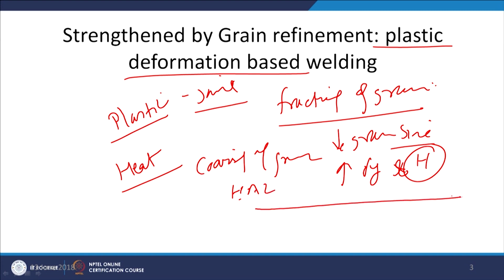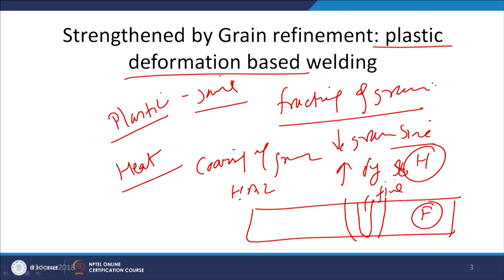So, what we may notice is that the weld zone is very fine due to the fracturing of the grains and the constituents, while the weld heat affected zone is coarser, and then the base metal is again finer because it has been strengthened by grain refinement. So, fine grain size in the base metal, coarse grain size in the heat affected zone, and very fine grain size in the weld metal.